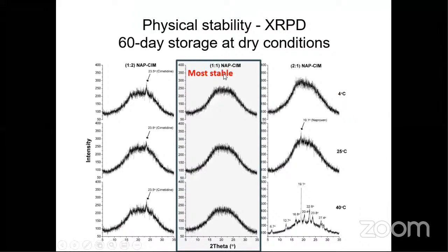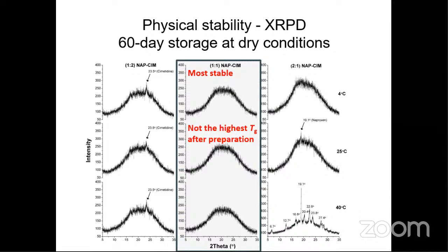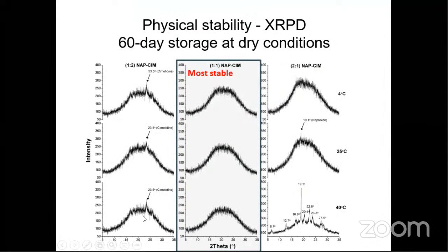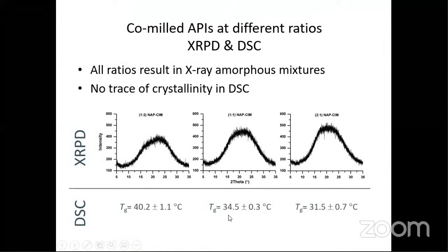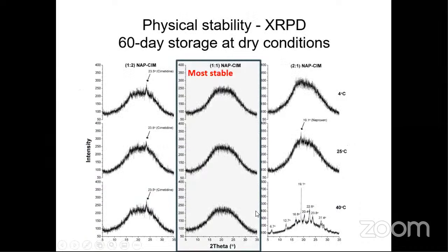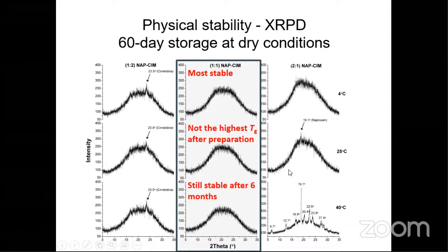The most stable one is the 1:1 molar ratio, still stable after 6 months. So from this experiment we can see that the highest Tg after preparation does not indicate the highest stability. The Tg only gives you a rough idea of stability, but you cannot judge stability based only on this information - you need to do a physical stability study.